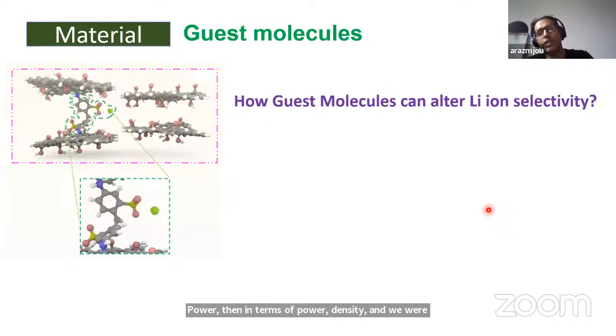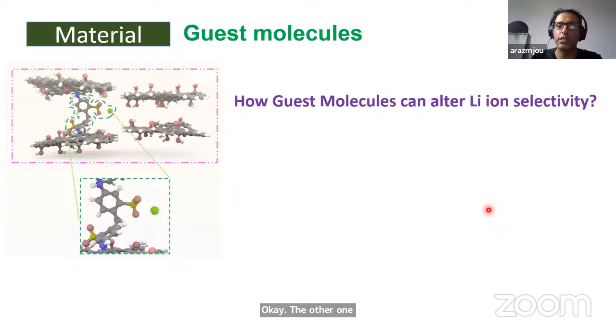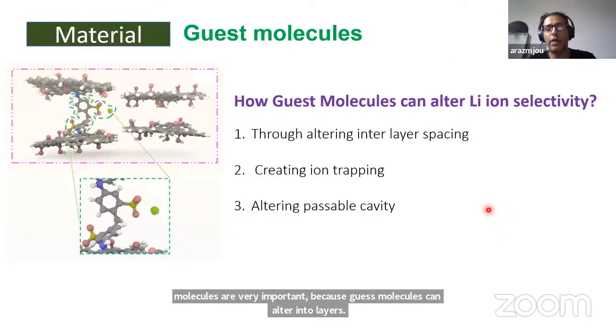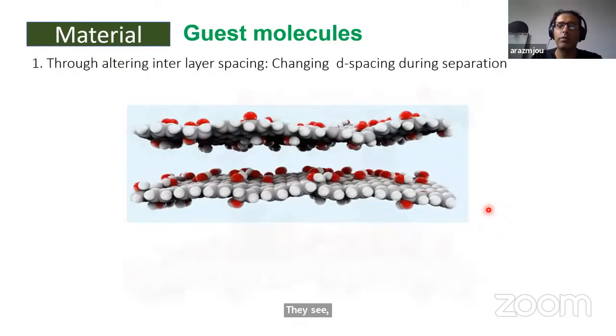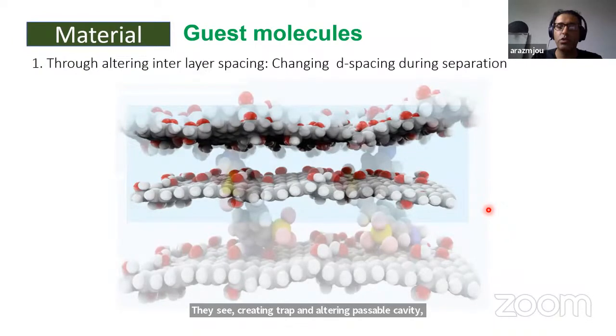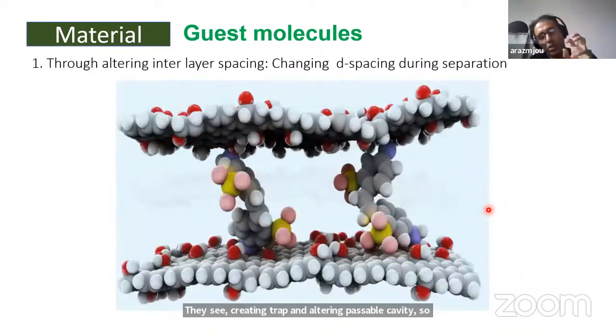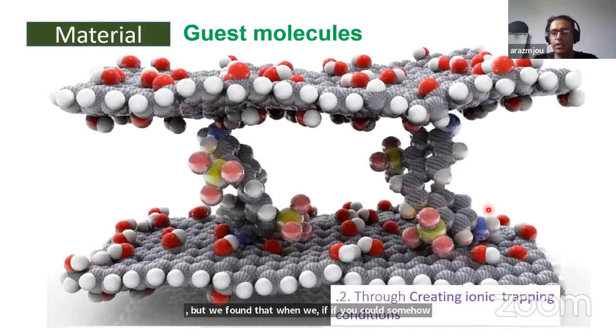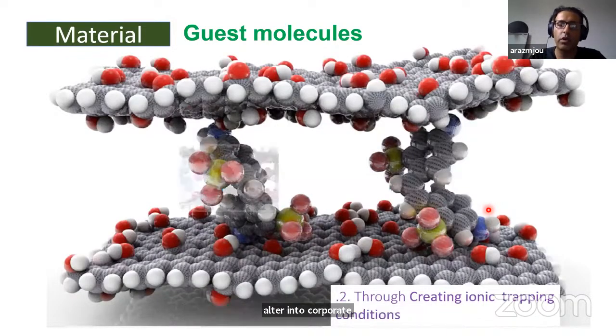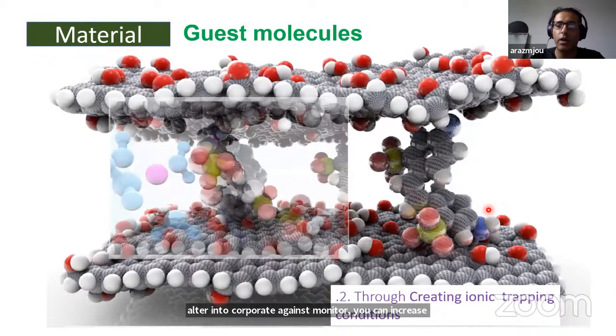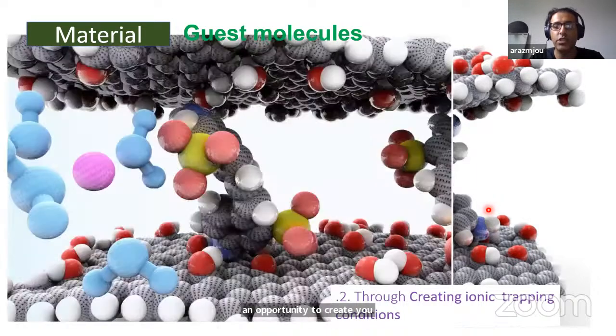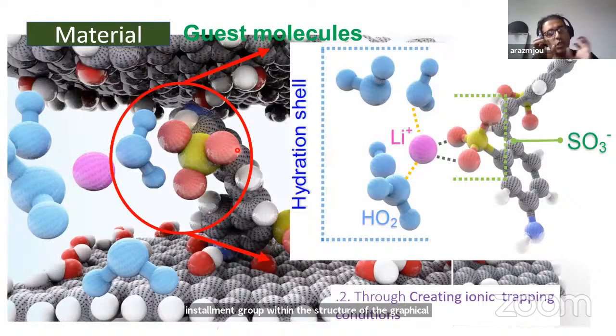Okay, the other one in terms of materials. So the guest molecules are very important because guest molecules can alter interlayer spacing, creating ionic trap and altering passable cavity. But we found that if you could somehow incorporate a guest molecule, you can increase or reduce the nanochannel size, and that provides an opportunity to create ionic trap. And as you can see here, the sulfonate group within the structure of the graphene oxide provides the opportunity to create ionic trap, which holds a specific ion and allows the other impurities to go through.